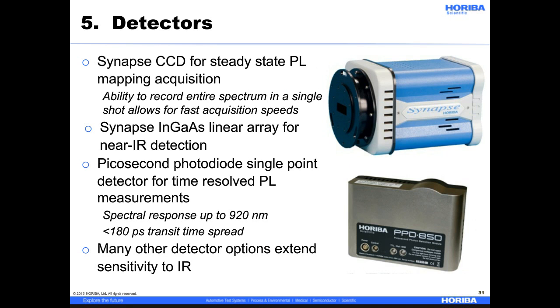In this set of experiments, a CCD was used to record steady-state PL single-point and mapped spectra across the surface. Because the CCD is able to record the entire spectrum in a single shot, fast acquisition speeds can be attained, which is especially important when recording mapping data. Although not used in the results presented here, the Synapse indium gallium arsenide linear array is also a good choice for steady-state PL in the near IR with response out to 2 micron. For time-resolved PL, a picosecond photodiode was used. The detector has spectral sensitivity up to 920 nanometers with a transit time spread of 180 picoseconds. There are many other detection options available that extend further into the infrared, including near-IR PMTs with response out to 1700 nanometers.